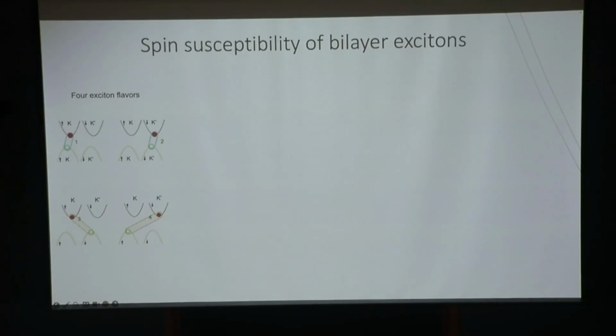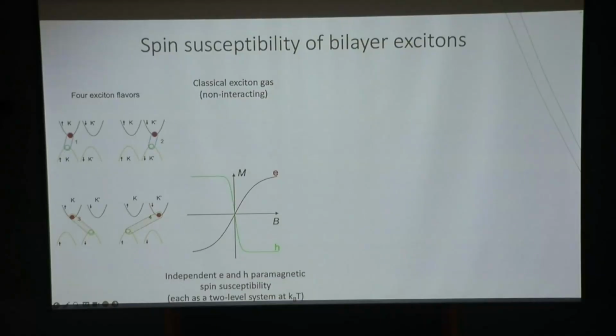If you have a classical exciton gas, where the excitons don't interact and talk with each other, and you just look at the classical thermodynamics, it turns out that the spin of the electron and the spin of the hole are not affected by anything else. They basically behave as a two-level system at a finite temperature, and they will just have a paramagnetic spin response. So we know they will have a tanh type of shape for polarization as a function of magnetic field. And because the electron and hole have different effective g factors, they will have different slopes, and they will saturate at different magnetic fields.